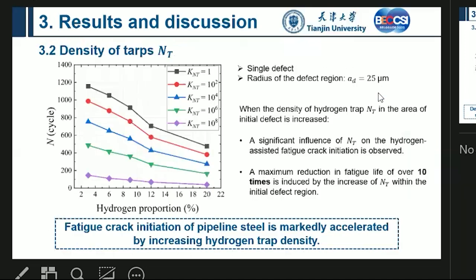Then we investigated, for example, the density of hydrogen traps. What's the impact on the fatigue life? We can take a look here. With the density of hydrogen traps increasing, the fatigue life is significantly reduced. You can see very quickly, the maximum reduction in the fatigue life may be over 10 times, induced by the increase of the NT in the initial defect region. So that means the density of traps is very important.